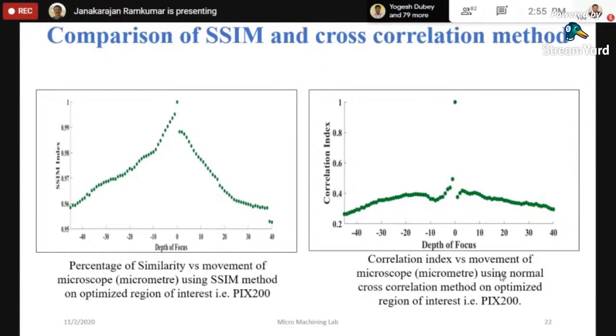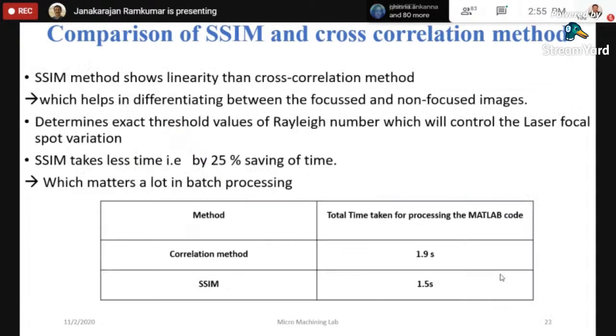When we computed the SSIM index and the cross correlation index, you could see that a very good correlation index was obtained from SSIM, depending upon the depth of focus. Comparing these two, the SSIM method shows more linearity than the cross correlation method, which helps in differentiating between the focused and the non-focused image, determining each threshold value of Rayleigh numbers, which will control the laser focal spot variation. SSIM also takes less time; 25% of the time is reduced.